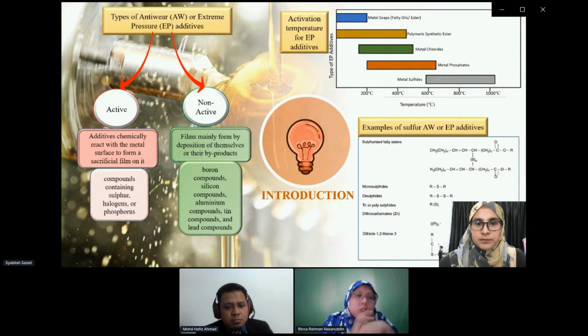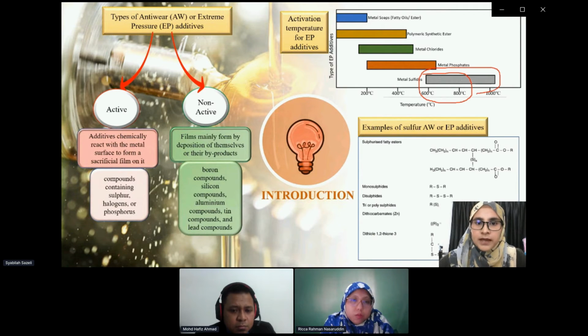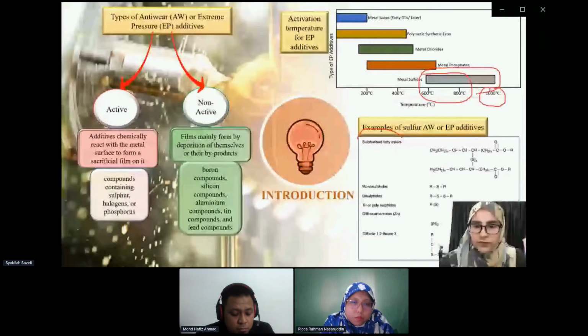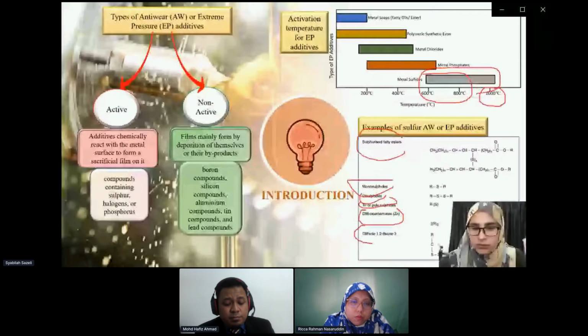From the activation temperature of EP additives, it shows that metals that contain a sulfide layer have the highest activation temperature. This indicates that sulfur additives are suitable for use in extreme pressure and temperature conditions. Examples of additives containing sulfur are sulfurized fatty esters, monosulfide, disulfide, tri or polysulfide, dithiocarbamates, and 1,3-dithiole-2-thione.